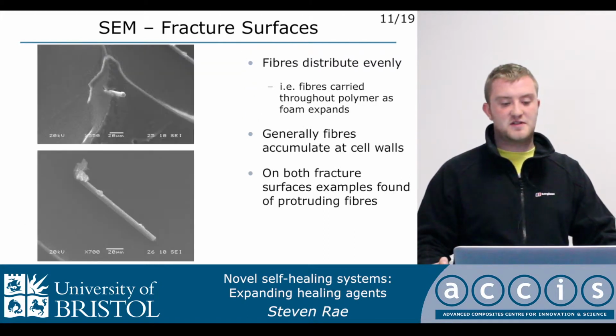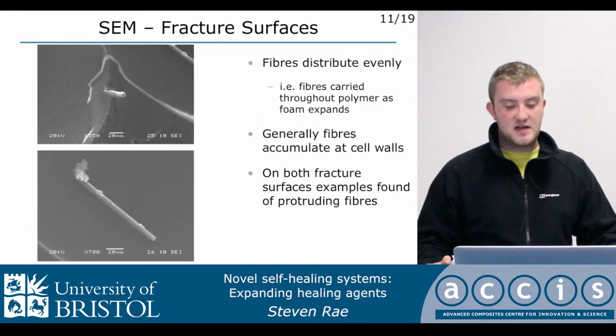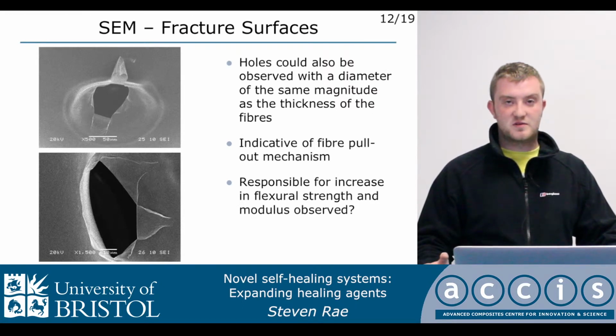On the fracture surfaces of the fibre reinforced foams, in each case we could find examples of fibres protruding from the surface and also holes whose diameter was of the same magnitude as the diameter of the fibres. From these images and the increase in performance we've seen, we're confident this indicates some kind of fibre pull-out mechanism.